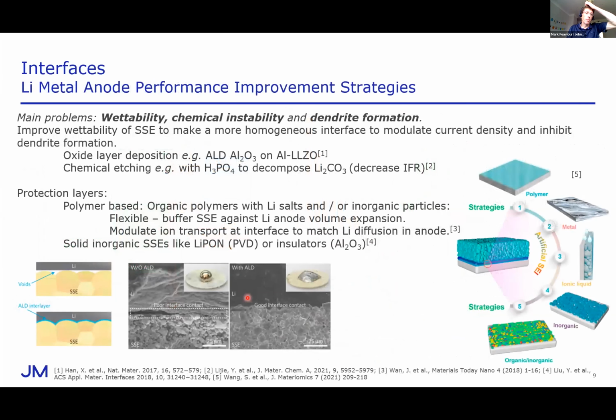So I mentioned the importance of managing to integrate a lithium metal anode, and there are a number of performance improvement strategies to overcome the main problems, which are wettability, chemical instability, and dendrite formation. I mentioned the dendrites earlier on, the thin tendrils which can lead to short circuiting. If we improve the wettability of the ceramic towards metallic lithium, we can make a more homogeneous interface, and that's going to modulate the current density, which is really important, and reduce the formation of dendrites.